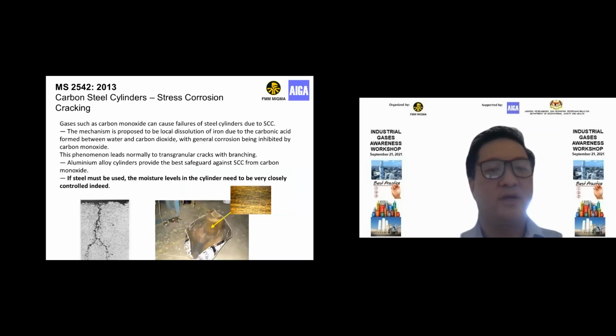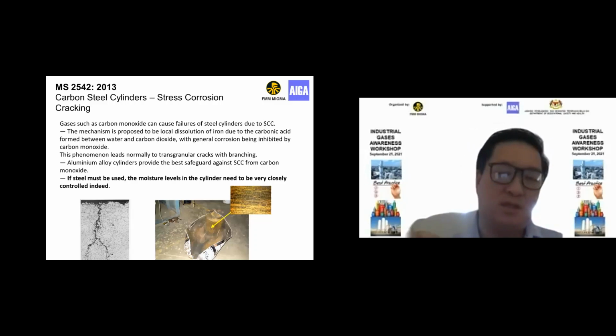Okay, stress corrosion cracking. Carbon monoxide. We do not recommend the use of carbon steel cylinders for CO gas streams because of the risk of stress corrosion cracking. There will be transgranular cracking appearing in the material itself that reduces the effective ability of the cylinder to handle the stress. Okay. Next big one.